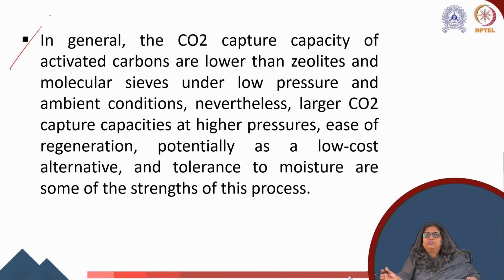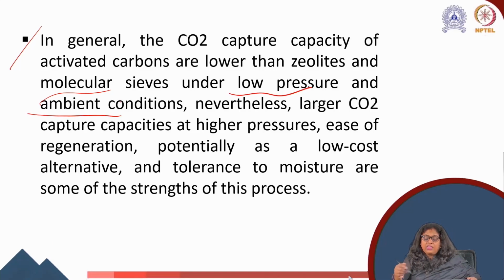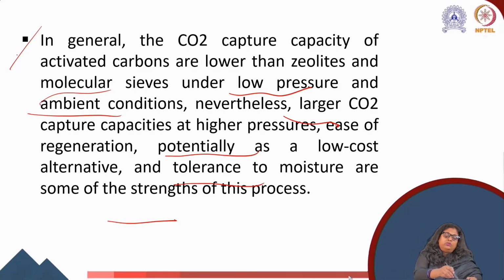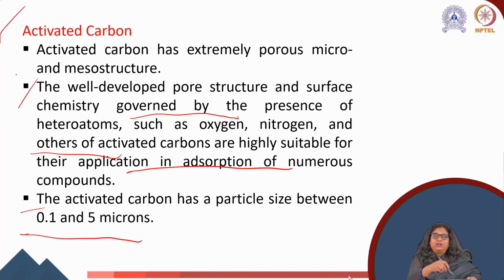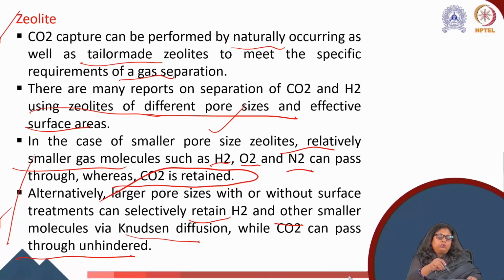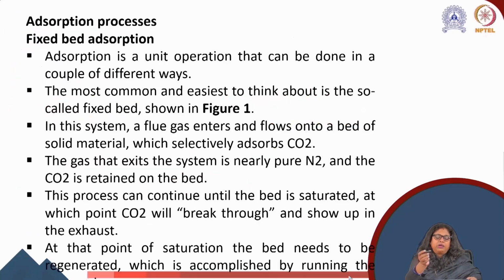In general, the CO2 capture capacity of activated carbon is lower compared to zeolite and molecular sieve under low pressure and ambient conditions. Nevertheless, larger CO2 capture capacities at higher pressure, ease of regeneration, potentially as a low-cost alternative, and tolerance to moisture are some of the strengths of this process. So this is about the three different adsorbents we talk about: molecular sieve, zeolite, and activated carbon.